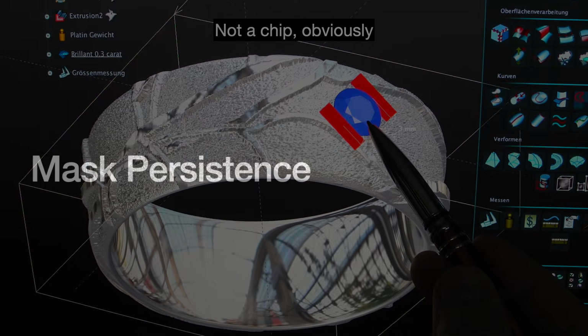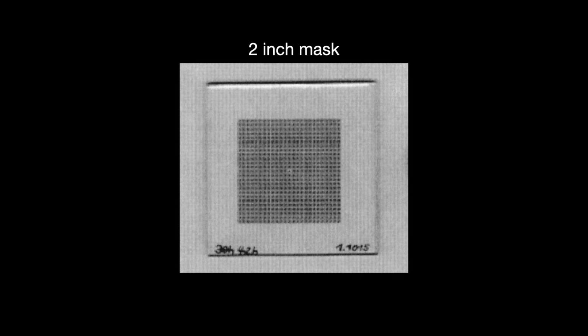With the contact printing method, constant contact between the working masks and the wafers caused them to quickly wear out. This not only means you have to replace the mask a lot, but you have to also increasingly watch out for print defects which ruin wafers and affect yield. As chips got bigger and defect reduction got more important, it got to the point where you could only use a mask for 10 wafer exposures and no more. This was not economically sustainable.